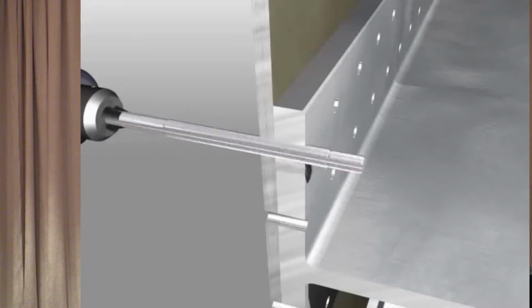So this area has gone from an elastic change into a plastic zone of deformation. The material a little further out is also into an elastic change, but as the mandrel exits, it's going to collapse back. When it collapses back, it's going to collapse around that plastically deformed material. And what that does is give you that zone of residual compressive stress.